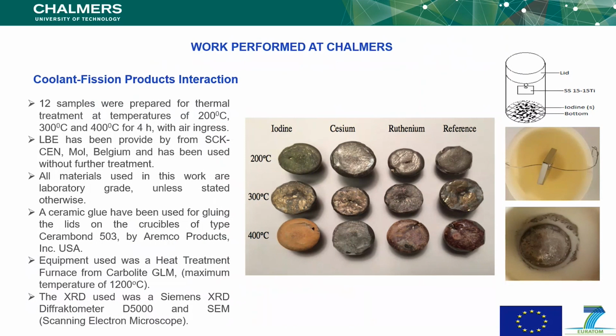And what basically we have looked at is what happens with the volatiles, the ones which are coming first out from the fuel when something has happened. So we looked at iodine, cesium, ruthenium, and then we have the reference, which is basically the samples we need to compare with. And then we look at different temperatures, what is happening and what we could collect from the surface. You see that the colors are varying quite a bit because we have had different materials forming. So if we now go to the next one,